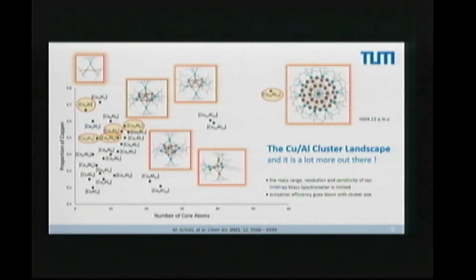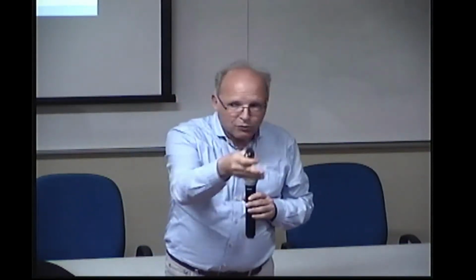However, there's an awful lot out there. Selectivity is per definition low in our synthesis. And it's also intentionally low because we do not know which of these aggregates and clusters is an interesting one. We don't know this one might have an interesting chemistry, catalysis or something. So rather than hunting for a specific one, we want to open the diversity of the chemical space as wide as possible. So we get pitch black solutions with a dispersion of many species where you cannot isolate easily each of them. If you try it, the distribution may change. So if we hunt for one of these, we change the others.